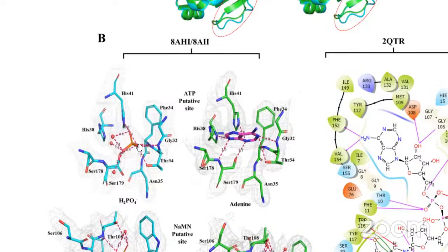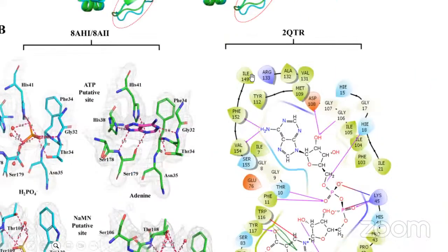The histidine residues, which have been shown to be productive residues necessary for the binding of the ATP substrate, interact with the adenine and also the phosphate group, forming hydrogen bond contacts. These residues are also evident in the Bacillus anthracis structure, as indicated by the 2D structure, which shows the corresponding residues: histidine 15, glycine 17, histidine 18. So they correlate, suggesting that the site that the phosphate and the adenine are bound to is the ATP binding site.